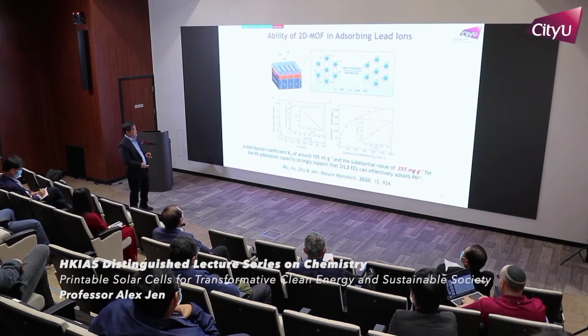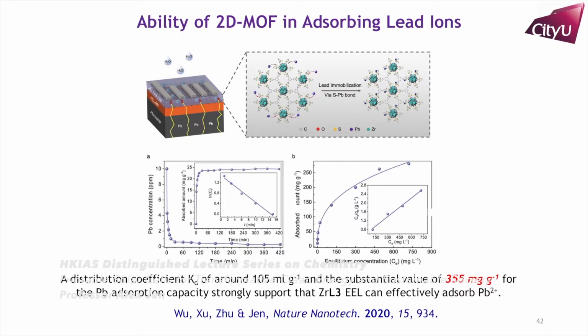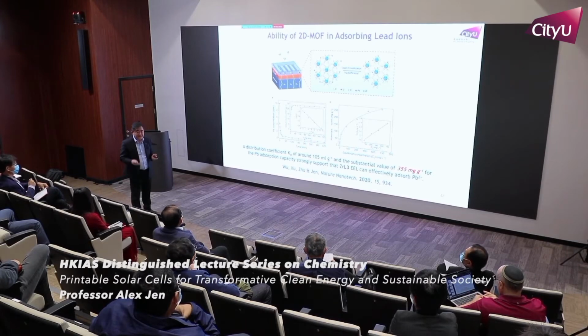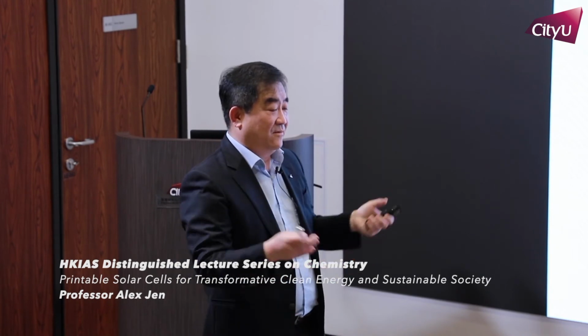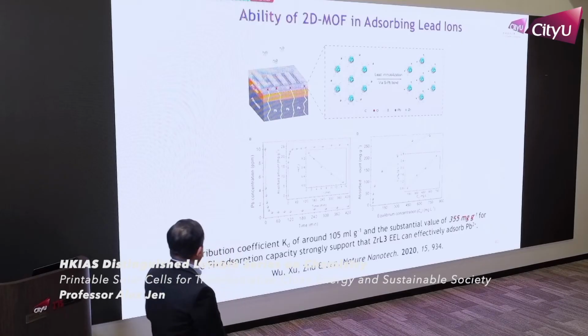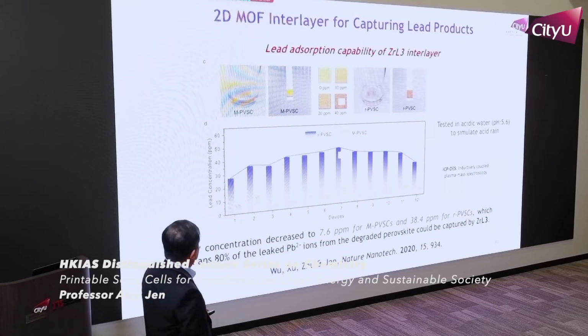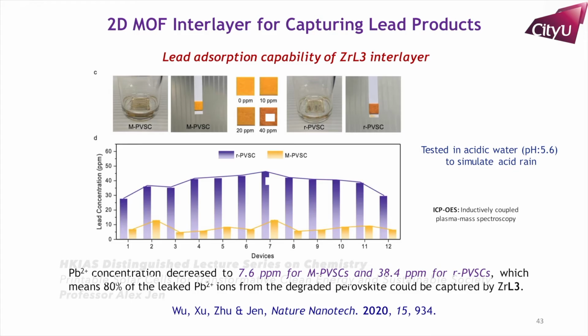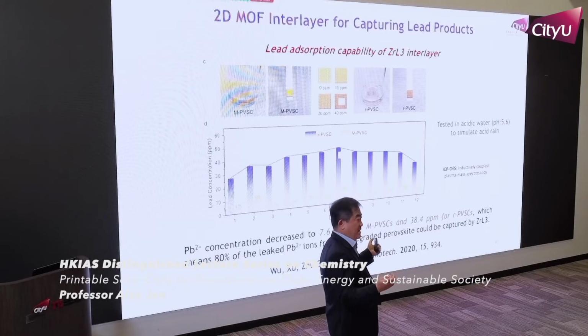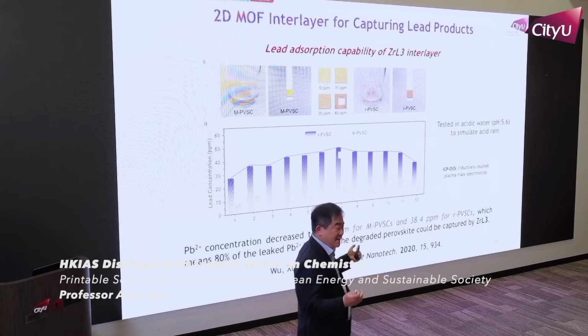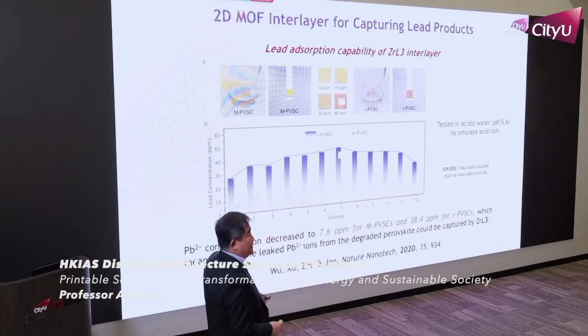This is also a slide to show you the absorbing capability, the kinetics of absorbing lead. How fast can it absorb lead? If it absorbs lead in 2 hours, then it's too late because it all goes down into the water. You need to absorb within seconds or minutes, then you have already absorbed most of your lead. So this is very rapid kinetics. As a result, we also simulated acid water by adjusting the pH value to about 5.6 to mimic acid rain, because rain can be acidic, so it may be more reactive to your perovskite.